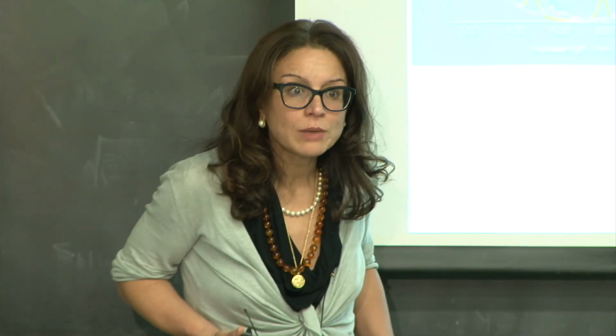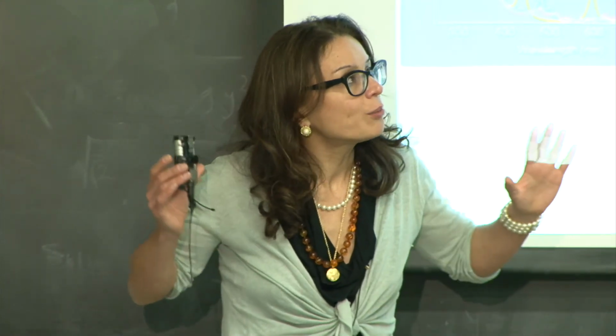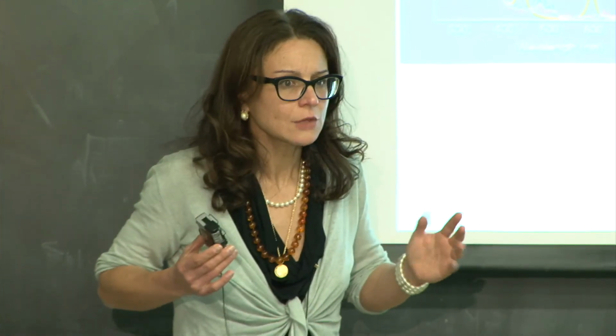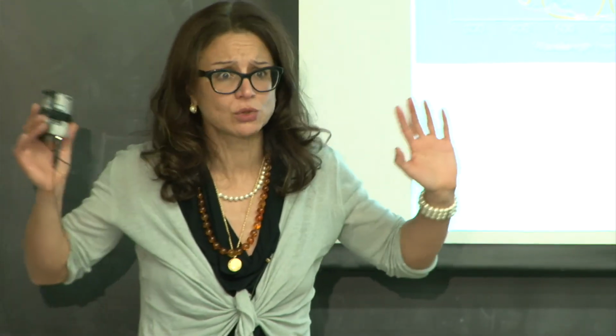And if you allow me, we can compare the organic solar cells or the organic solar battery, but not too much. The two environments are completely different. In one case, we are solid state. In the other case, we are immersed in an aqueous environment in presence of salts with a certain ionic strength. So I don't want to push too far the comparison, but we were surprised about the stability in light conditions.